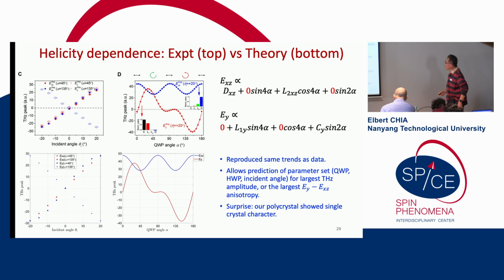So recently, our theory colleagues did a photocurrent calculation based on the photon drag effect and taking into account the symmetry of our sample. And so you can see that this is our data, and this is the simulation. So you can see that the trends can be reproduced as before.